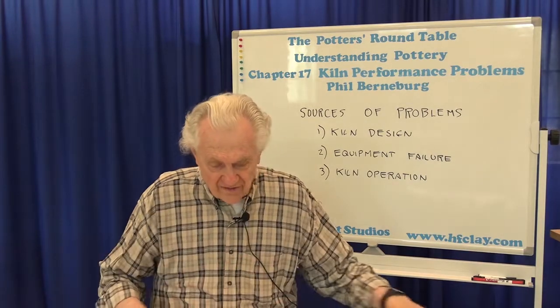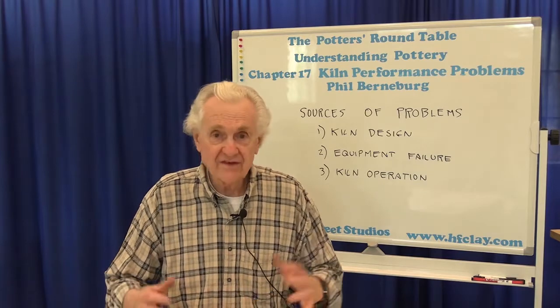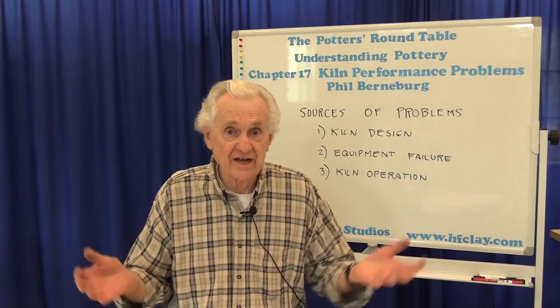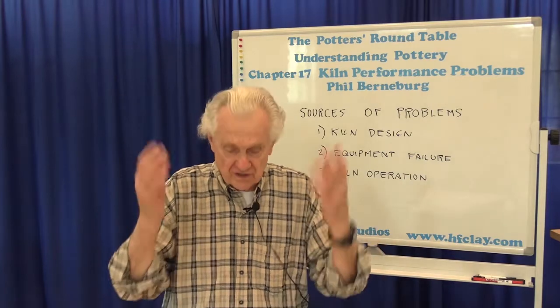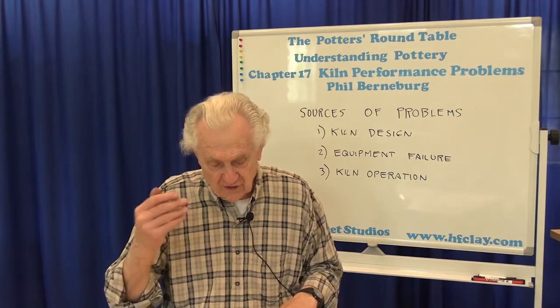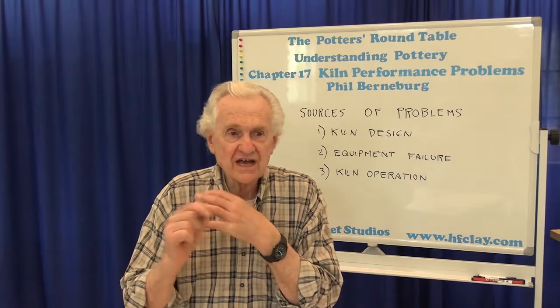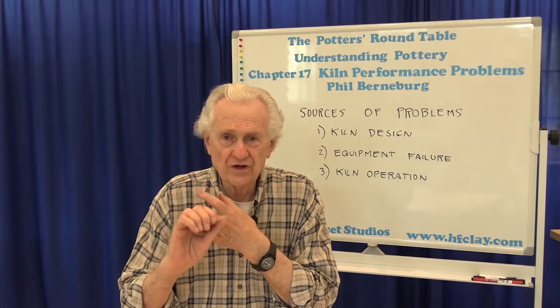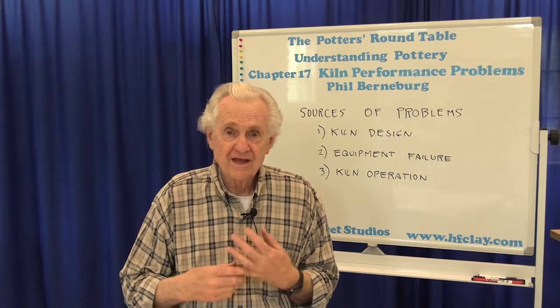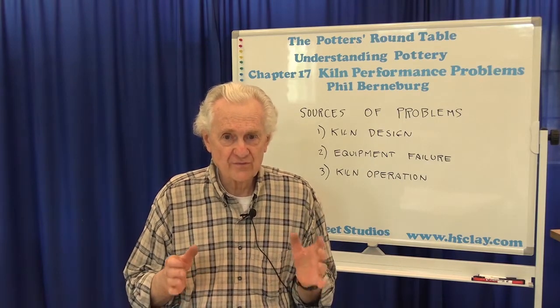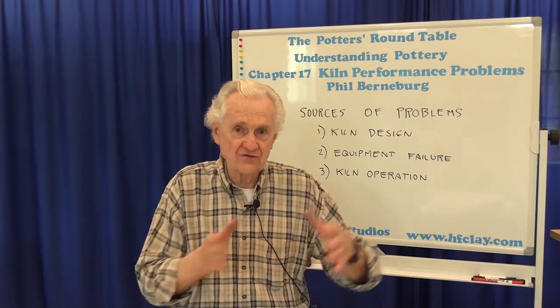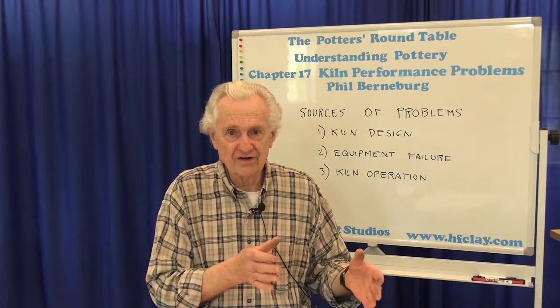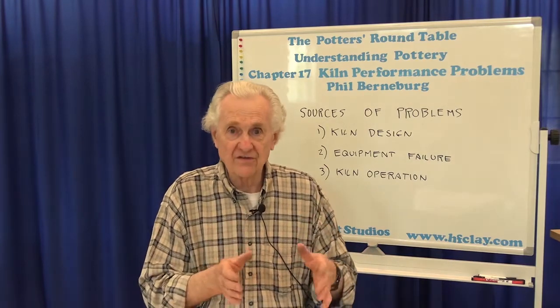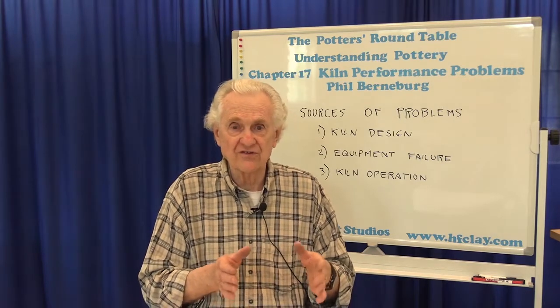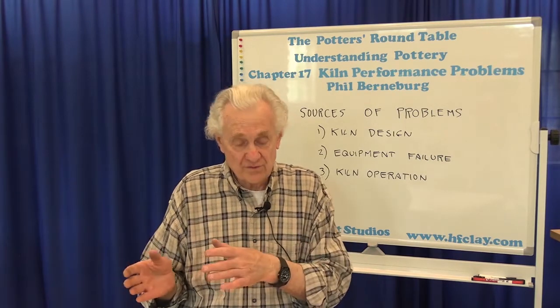Again, one of the common problems is slow temperature rise. If you think about it, all it means is I'm not putting in enough heat fast enough. I can't get the temperature to go up. This could be a combination of equipment or operation. In terms of operation, you have to think about the quality of the wood you're burning. Is the wood wet? If you're using wet wood that hasn't been thoroughly cured or dried, it takes heat to dry out the wood, and before the wood can burn, it has to get dried out. It takes a lot of heat to evaporate that moisture, so that's a waste of heat, going to evaporating water and not raising the temperature of the kiln.